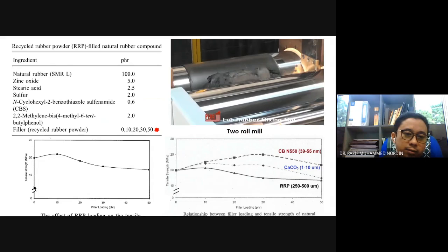This is my recyclable powder, and over here I use recyclable powder of about 250 to 500 micrometer. With increasing filler loading of recyclable powder, the strength of the natural rubber composite decreases. This is because the recyclable powder is in an agglomerate form, so the binding process does not occur. The initial increment of strength at 10 phr is just due to the particle size of the recyclable powder.